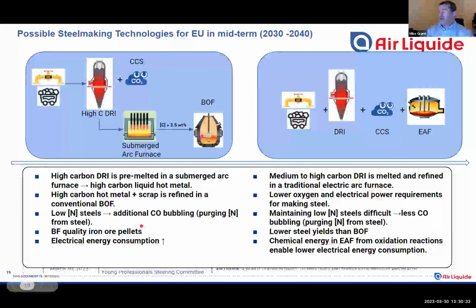Now, there's two processes or two routes being anticipated here in Europe. One of them is the high carbon DRI being charged into a submerged arc furnace, which is producing a high carbon hot metal. And this high carbon hot metal will be further refined in the BOF, just like they were doing in the first place. To get the carbon in the DRI, of course, you need natural gas. This natural gas deposits carbon in DRI, and you need at least 3.5 weight percent carbon in the hot metal in order to be able to use it in the BOF.